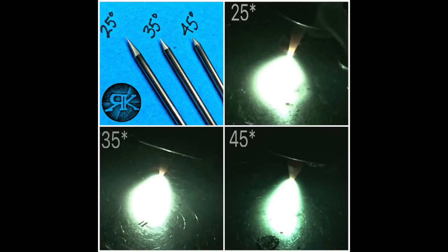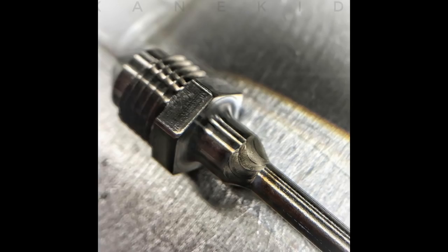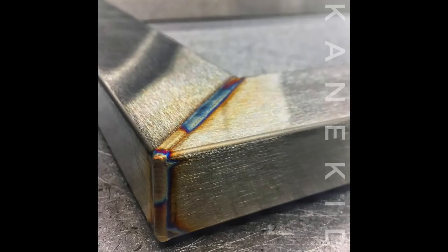I always think it's a pretty good rule of thumb to try not to go thicker with the filler metal than the thickness of the metal that you're welding. Now, that obviously changes when you start doing multi-pass welds on 3/8 thick or half-inch thick. But if we're talking about sheet metal, if you're welding, say, 40 thousandths, a 1/16th filler metal sometimes is a little bit big. It draws a lot of heat out of the puddle when you dip it in. And so going with a .045 wire might be a little bit better.